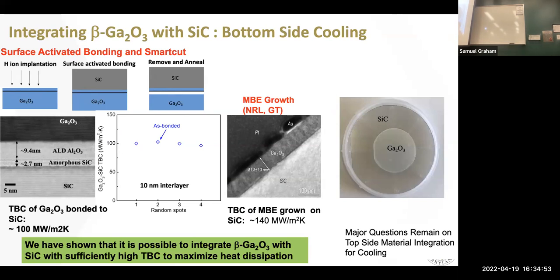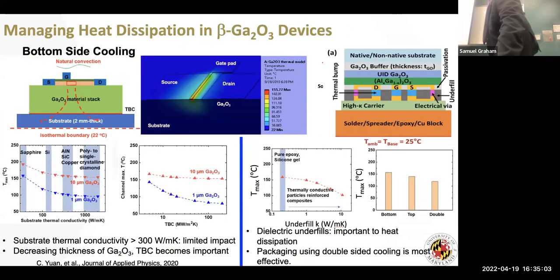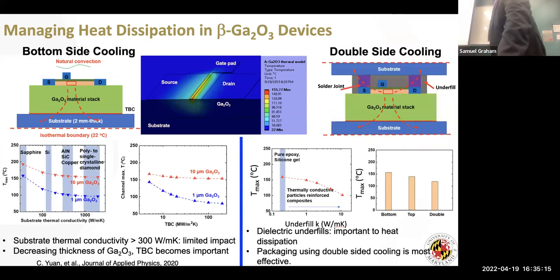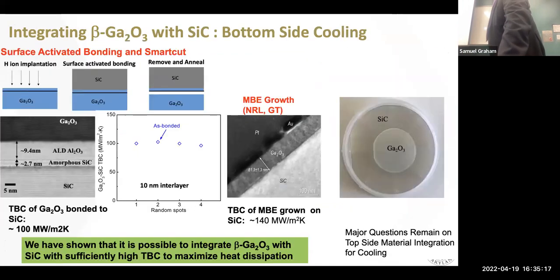What you're seeing here is that this thermal boundary conductance is around 100 megawatts per meter squared K. And you can see that if I can get up to here, then it starts to flatten out. So we're pushing the boundaries of where that technology needs to go in terms of making those devices by doing this bonding.